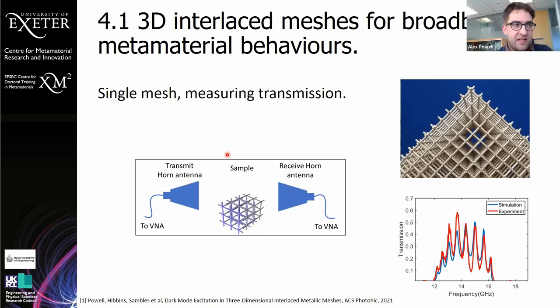Well, the conductivity, off the top of my head, it's copper flakes in paint, or copper-coated silver flakes in some kind of solvent, actually a water-based solvent, surprisingly. Its conductivity was stated by the manufacturers to be something like 10 to the 5. And we found that matched pretty well with our simulations. When we simulated 10 to the 5, it matched pretty well with the experimental results that we got. So we didn't push it further by doing four-point probe tests or anything like that, which I think you would want to do for a more rigorous study.